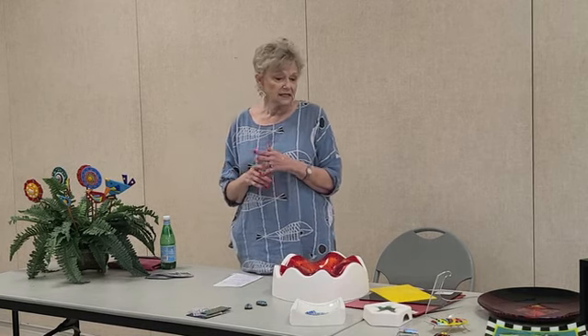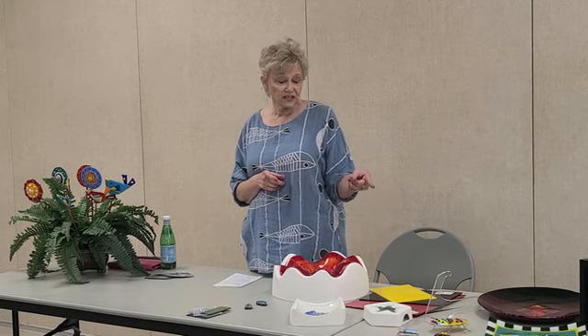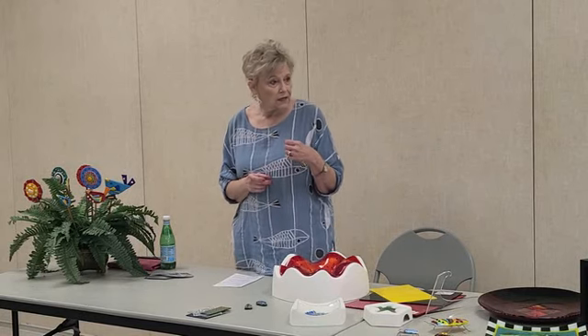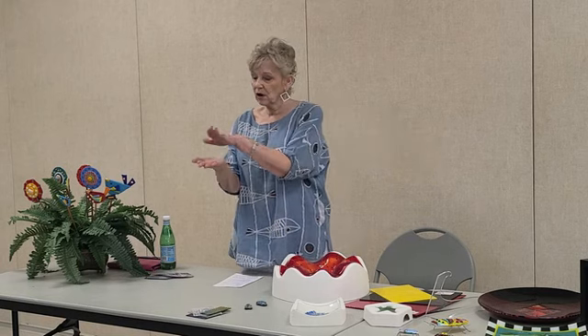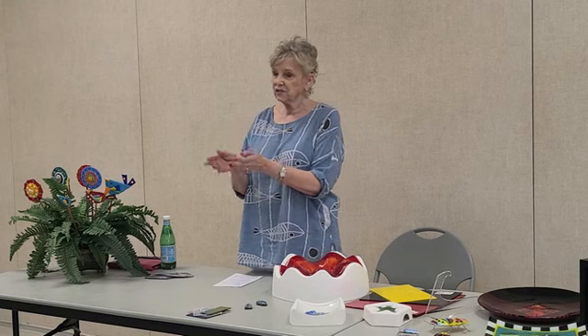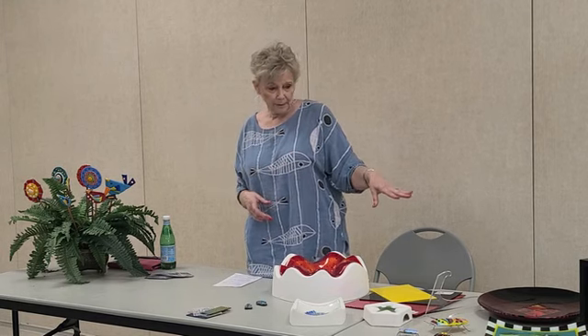And then decide if, in this case, it wasn't built in such a way that it was going to have bubbles in it. Like the piano would have had bubbles had I not, because they're all just pieces like this. This one down here were pieces like this, so the air could escape, the heat could escape, so I didn't have to worry about the bubbles.